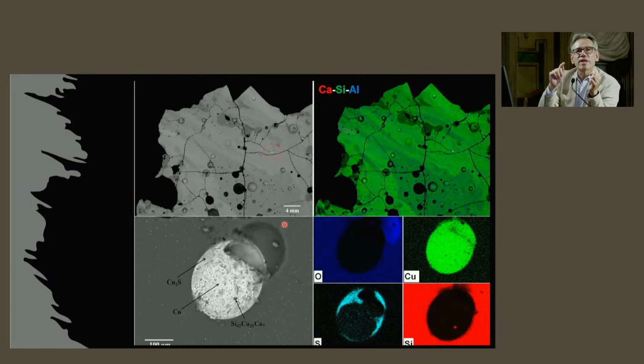But if you look more carefully, you can see the presence of sulfur at the borders, indicating that you have copper sulfides associated with the metallic droplets. And if you look even more carefully, you can see that there are small metallic ternary alloys present inside the droplets, in this case a silicon-rich copper-calcium alloy.